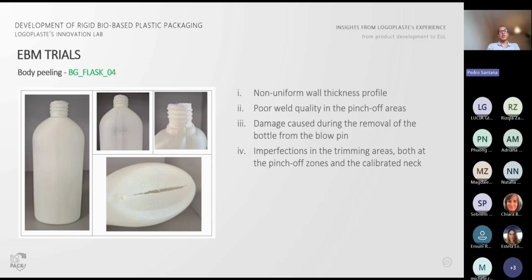The same situation occurred with the cosmetic bottle for body peeling. Since this packaging has a geometry very similar to the sun care, the processing challenges were almost identical. Once again, issues such as non-uniform wall thickness, poor adhesion in the pinch-off and trimming areas, and difficulties in material fusion and extrusion were observed. As in the previous case, defects were also visible in the area where the blow pin was removed, compromising the final quality of the packaging in both appearance and performance.